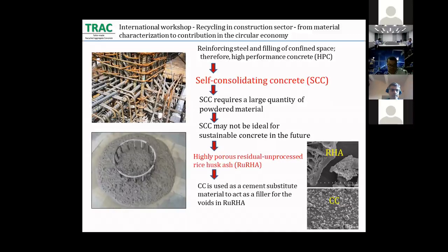Rice husk ash can be substituted at 15 weight percent in Portland cement, similar to conventional concrete. However, most importantly, it is difficult to control the reactivity and fineness of rice husk ash, and it is normally produced with low reactivity and high porosity, especially as-received, unprocessed or untreated rice husk ash. This factor increases the water requirement and consequently decreases the strength and durability of concrete. The first issue can be solved by controlling the burning time, temperature level, and amount of oxygen in the burner. However, the second challenge is difficult to solve.